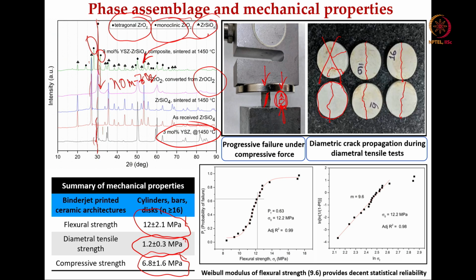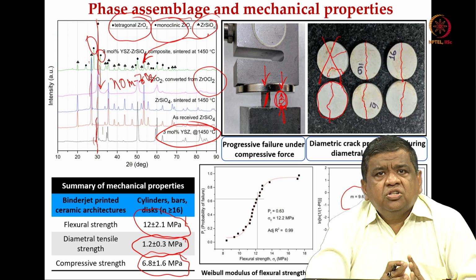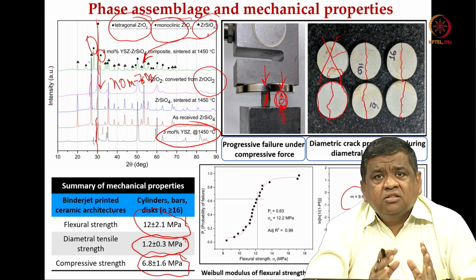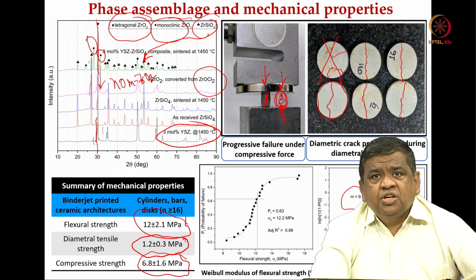And then we used weakest link fracture statistics, as I explained in the last lecture in the context of binder jet 3D printing of Ti6Al4V. We have found that the Weibull modulus for this binder jet 3D printed zirconia is not bad. It is 9.6. Actually, it is a relatively good Weibull modulus considering a very porous zirconia ceramic. However, the mean strength is fairly low, around 12.2 megapascal. So, we consistently use this weakest link fracture statistics for any of the 3D printed structures, whether metallic or ceramic samples, primarily because of the good amount of porosity in the 3D printed structure.